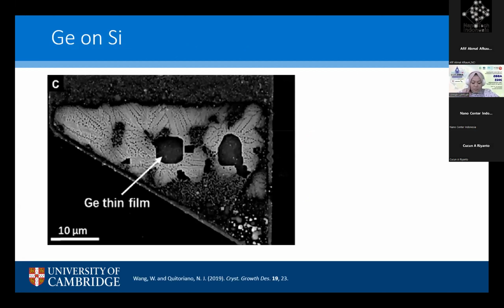Okay, so this is how the sample looks after epitaxial growth on silicon at 375 degrees C with germanium hydride flow rate of 5 SCCM for 1 hour. From the top view SEM here, we can see that the microscale germanium thin film was successfully formed on the silicon substrate.